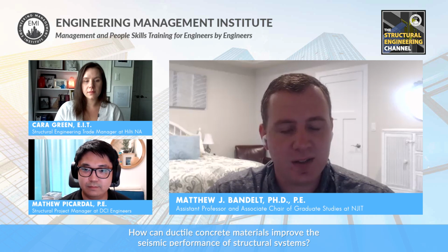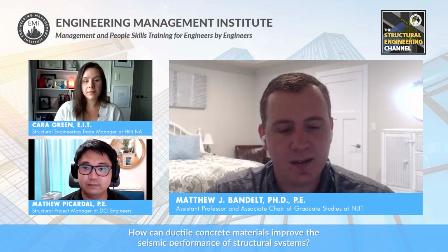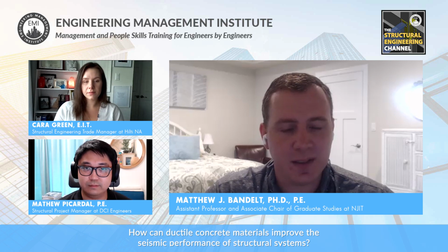And then the second advantage is it has excellent shear performance. In seismic design, shear demands can significantly influence your design decisions. In traditional concrete, you develop those diagonal tension cracks, and then you rely on stirrups or confinement reinforcement to carry the stresses. With the ductile concretes, because you have those fibers in there, they restrain the crack opening and thereby increase the shear strength and shear deformation capacity.